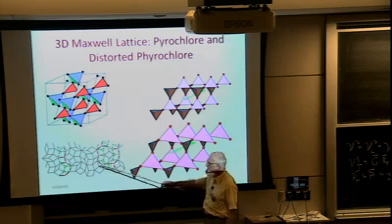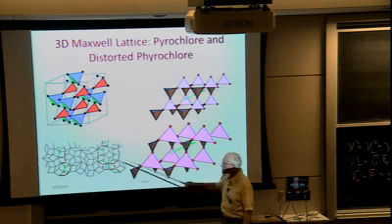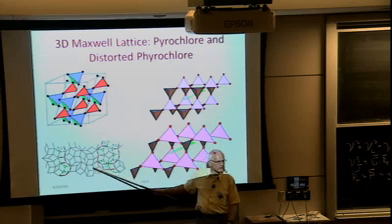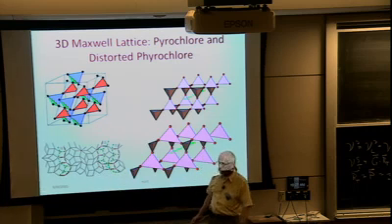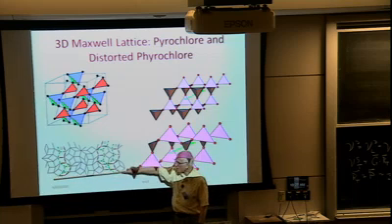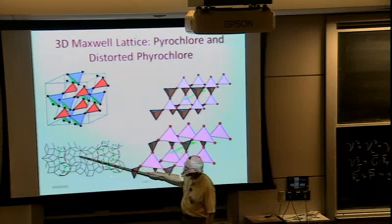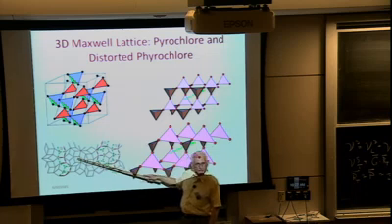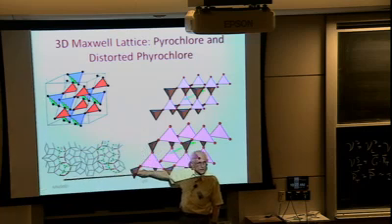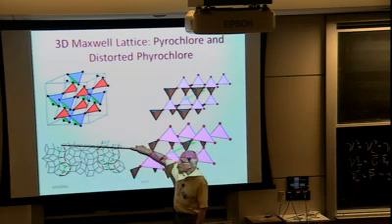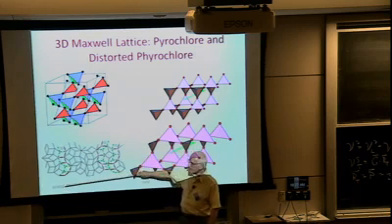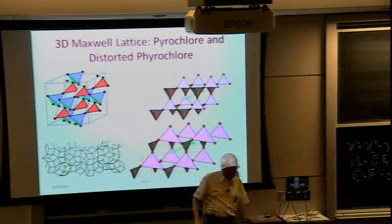Now, this is a rational approximant, so you get it periodically repeated in all directions, and you can ask, what are the properties of that? And it turns out that this is full of Weyl modes. But it also has the property that if I just look at q equals 0, which means I'm looking at this cell alone, then depending upon how I randomize these sites, or in the case of jamming, what particular structure you've created in your jamming process, you get a different number of zero modes on this side than that side, which is an indication that they have a topological character.